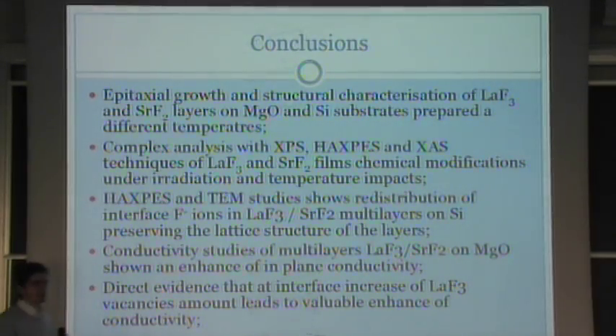At the end, I want to say that through these years, we were able to understand how fluoride ionic conductors grow and how they change under different irradiation. They are actually prone to irradiation changes and temperature changes, and we were also able to show that by controlling irradiation or structure changes, we are able to induce changes in the conductivity of multilayers, which is a good result, I think.